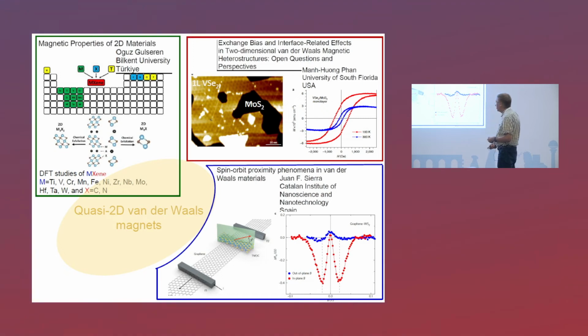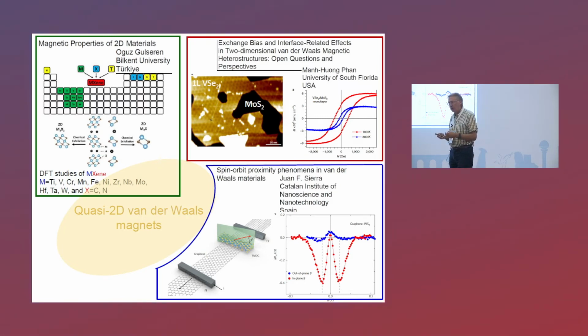Also a combination of a non-trivial conductor, which is graphene, with a magnetic van der Waals material like transition metal dichalcogenides was illustrated in a talk by Juan Sierra from the Catalan Institute for Nanoscience and Nanotechnology, where they found that the spin currents generated with the aid of these ferromagnetic electrodes on this stripe of graphene can be manipulated by the layer of the transition metal dichalcogenide in the presence of an applied magnetic field, where one can change at will the spin polarization of the carbon from out of plane and turn it to the desired angle depending on the field strength applied to this bilayer structure. And in this case, of course, the anisotropy of the spin lifetimes was found, and it is very strong for certain experimental conditions.